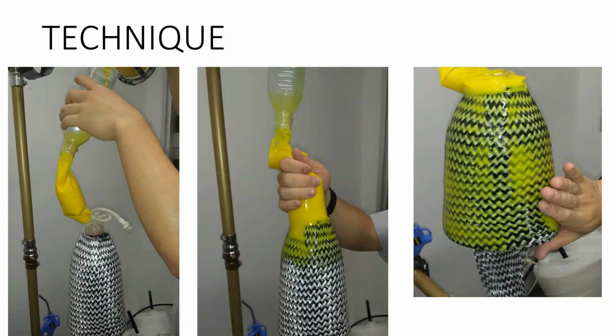Now sometimes we'll have enough layers, but it could be what we inadvertently do. Many times I've seen people laminate where they pour in the resin, they have the vacuum on, and then they untie the bag and quickly squirt in the resin. They don't give the resin time to saturate all the material. So what happens is they actually trap air on the bottom of the socket. And this will prevent the material from saturating, and then you get a weak point.